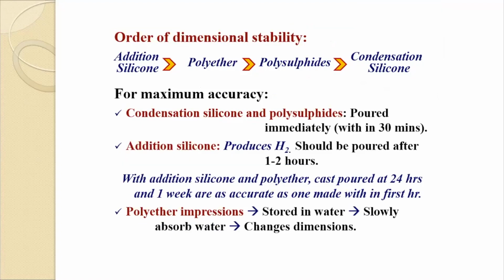Then coming to the order of dimensional stability. Your addition silicones have the maximum, then polyether, then polysulfides, then your condensation silicones. Like I told you earlier, here we can see that polyether impressions, if stored in water, slowly absorb water and change dimensions. So this you have to keep in mind with them. And like your addition silicones, they produce hydrogen. So they should be poured after 1 to 2 hours.